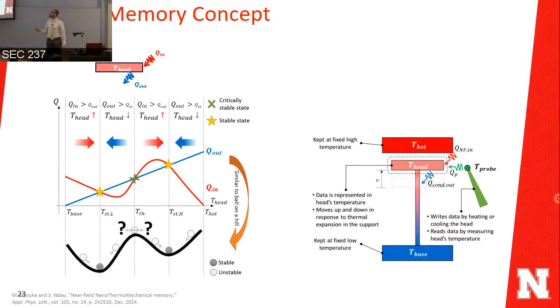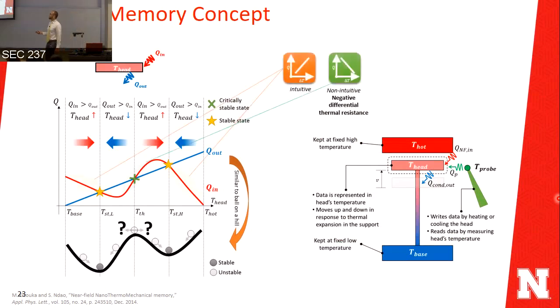So we engineer the heat input to the head via near field thermal radiation and try to make it take this weird shape. This shape has a region where negative differential thermal resistance happens, which is a counterintuitive phenomenon. Usually for heat transfer, the higher the temperature difference, the higher the heat transfer you expect. However, in this region, the higher the temperature difference, the lower the heat transfer. How can you achieve this? By coupling the near field thermal radiation with the expansion in this microstructure.